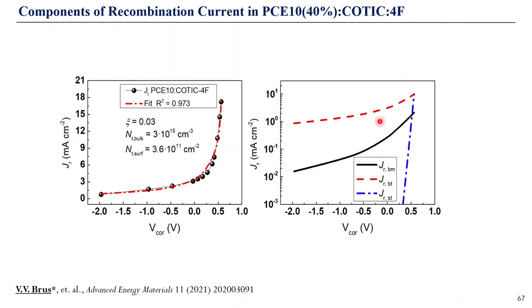and then when we analyze individual contributions from recombination mechanisms to total recombination current, we see that indeed trap-assisted recombination in the bulk and at the interface have pretty much equal contribution, and their contributions are dominant in comparison to bimolecular recombination at open circuit voltage. That is because of relatively low concentration of charge carriers in the active layer and quite low Langevin coefficient for bimolecular recombination. It should be mentioned here that when we go to lower concentrations, this relative contribution of bimolecular recombination should drop even further, because bimolecular recombination is proportional to concentration of charge carriers in second power. So as it drops, its relative contribution will drop even further.